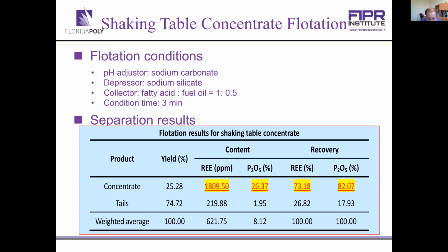If we do flotation on the gravity separation concentrate, the rare earth concentration is further increased from 500 ppm to 1800 ppm. And the P2O5 content also reached 26%. And the P2O5 recovery is 82%, rare earth 73%. This is from the gravity separation concentrate.